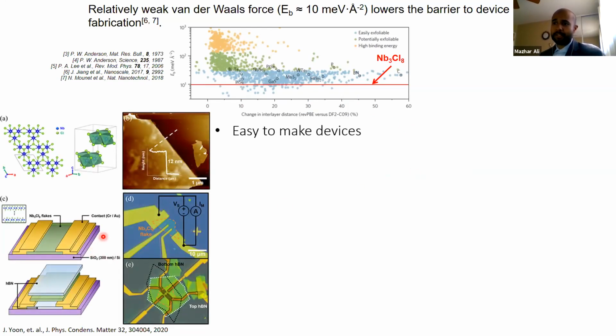So we started with some basic investigations and we made our sandwiches. Not superconducting, we started with some basic transport exploration. And we found that, one, it is easy to make devices. And very happily, odd numbers of layers break inversion. So it's a 6-layer repetition of the unit cell and they stack slightly off each other. So if you grab an odd number of layers, the stacking is not inversion symmetric. So while the whole bulk compound is inversion symmetric, if we take our exfoliated flake down to an odd number of layers, like let's say 3 layers, which we will do in the next slide, then you can break inversion.